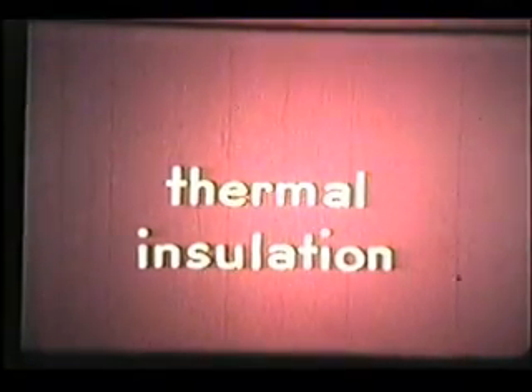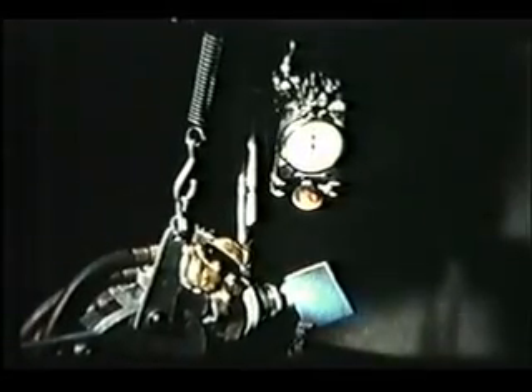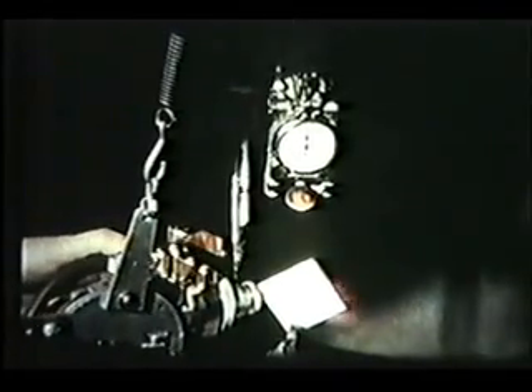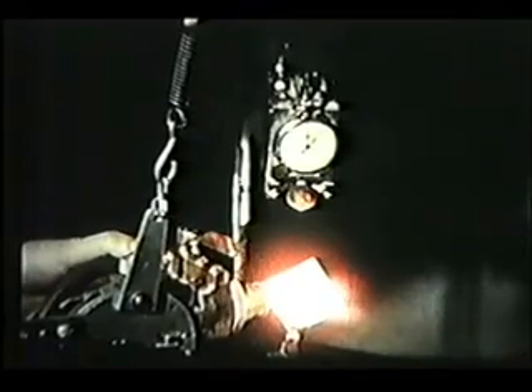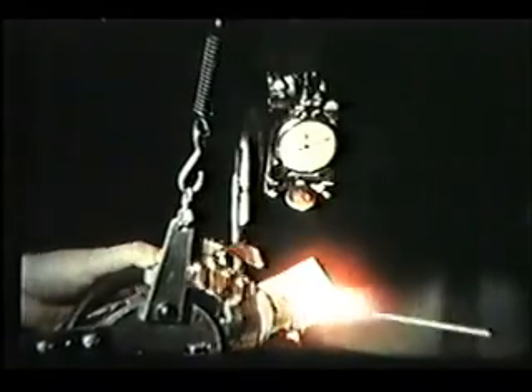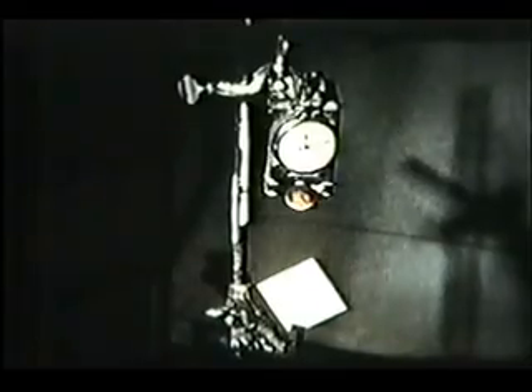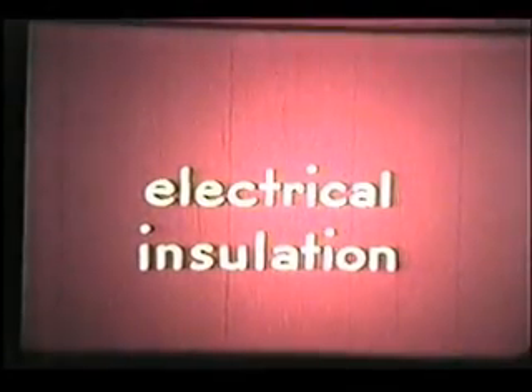To illustrate the excellent insulating characteristic of the Rockide coatings, we first show you a metal plate being exposed to an oxyacetylene flame for approximately 6 seconds. The 1/8 inch thick steel plate is burned through, while after 10 seconds of similar exposure, the Rockide coated plate with 25 thousandths of an inch thickness of Rockide A has provided the base metal with an effective heat barrier from the over 5,000 degree flame under these non-equilibrium conditions. The plates side by side show the slight fusing of the aluminar coating, but when the plates are reversed, there is little or no discoloration of the ceramic protected plate.